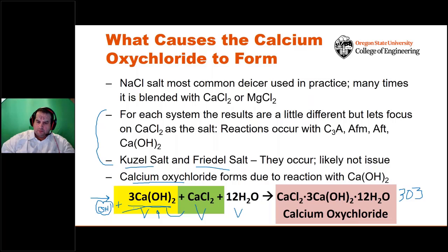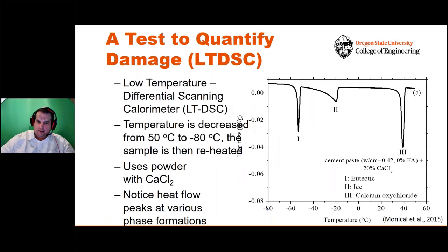So just to put this into perspective, we freak out about designing our mixtures to withstand water transforming to ice, which is about a 9% volume change. But here we have a 300% volume change that's going on in the system. Clearly, this can be leading to some of the damage.